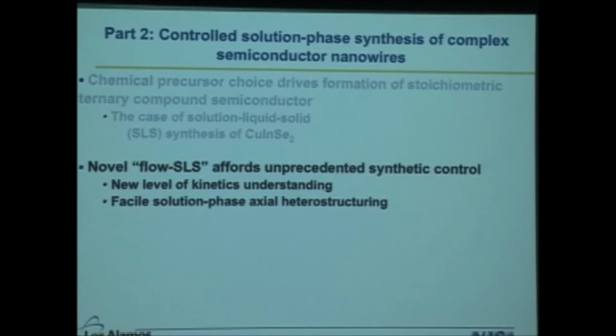And so what we sought to do was to make SLS a little bit more like VLS, or vapor liquid solid growth, which has the advantages of being able to introduce precursors in a more controlled fashion to your molten catalyst flux, and to remove byproducts, because it's a flow-based technique. You're flowing in gaseous precursors, they're reacting, and then byproducts are disappearing. A new reactant can come in. And so the VLS world is able to more easily create axial heterostructures, for example. You can pass in one precursor, create a segment of one composition, flow it out, flow in another precursor, create the next segment, and so on and so forth. We just really haven't been able to have that level of control in the SLS approach.